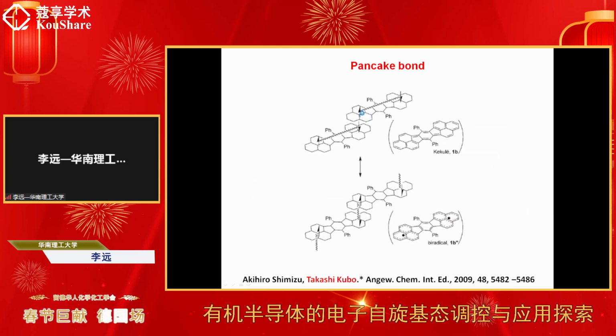You can see the intermolecular interaction, the pancake interaction between the two molecules, and the ESR spectrum of this kind of diradical as a powder. In the solid state, the ESR signal will be weak. However, the diradical character is in fact very high.